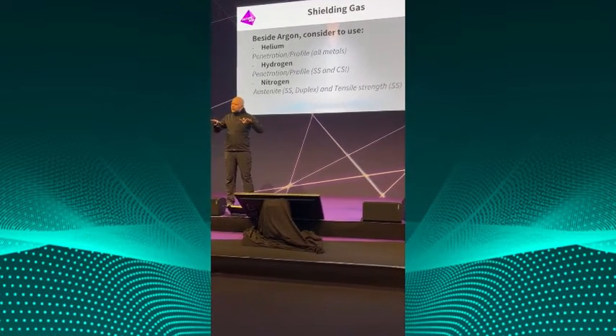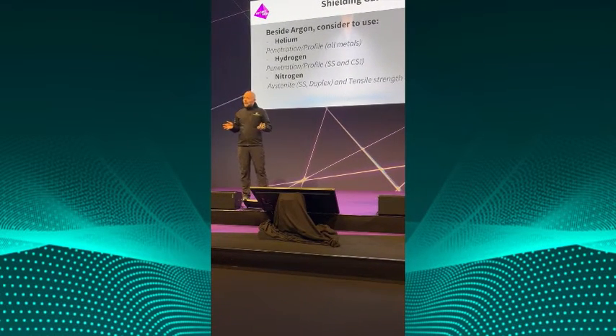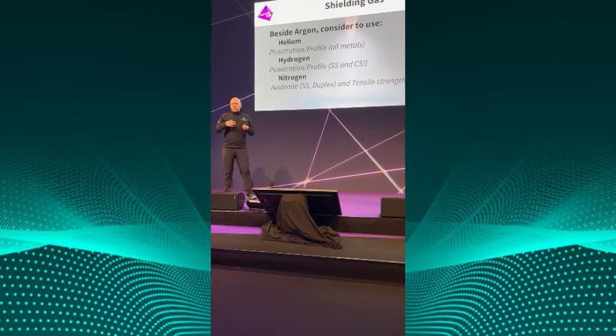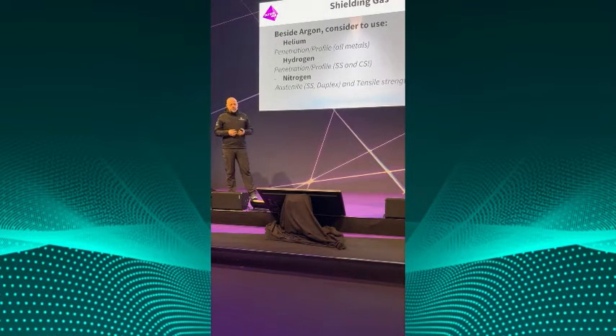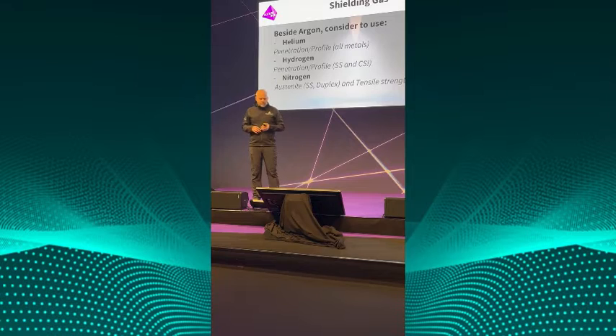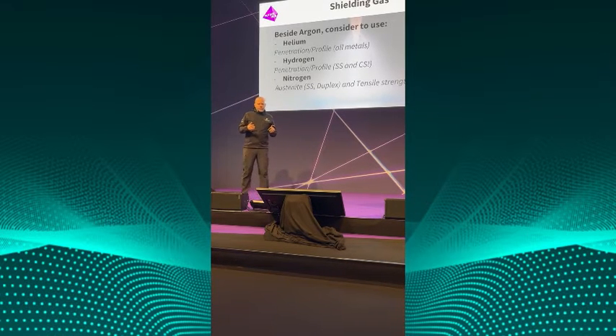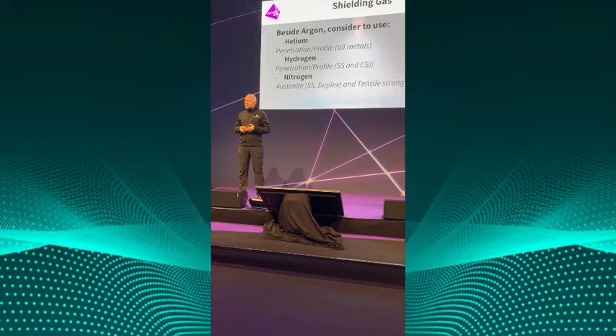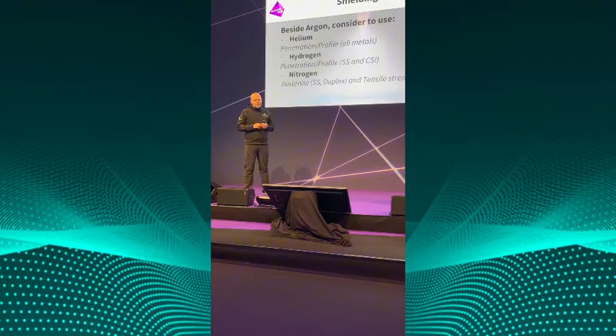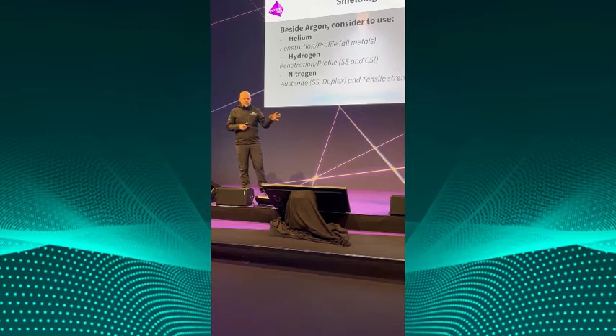As an example, increase penetration or create a more preferential penetration profile in all metals. That's kind of the positive thing. Even the most sensitive base materials can be welded with helium. Hydrogen can do about the same trick, although it's far more efficient. Against many notations in the literature, the density of the gas is not essential for the heat conductivity. Hence, hydrogen is, at room temperature, about twice as efficient as helium, but it's limited almost always to stainless steel. But I can say you can also use it in carbon steels.